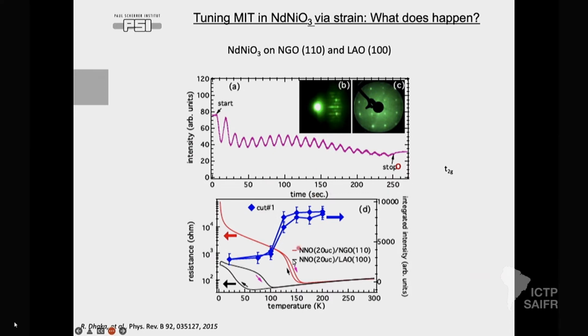All right. So the transport shows what was reported for the 20 unit cells grown on the tensile strain NGO: there is a pretty sharp metal-insulator transition at around 150 Kelvin. When you grow the film on the LAO, there is a similar trend in the metallicity, with almost overlapping curves, and then the metal-insulator transition is lowered. But overall, even at low temperature, metallicity is still there, so the system is not really insulating. In the NNO grown on NGO, the resistivity is shooting up, while here it is not. There is still a way for current to go through the sample.